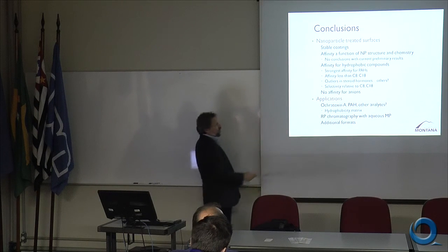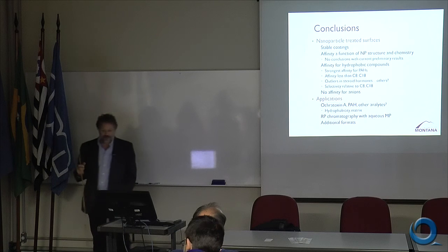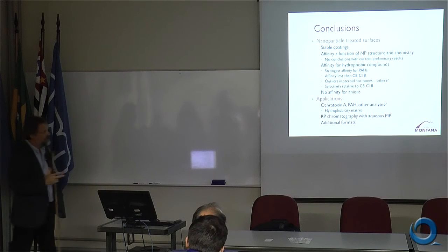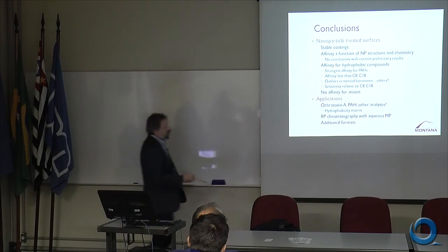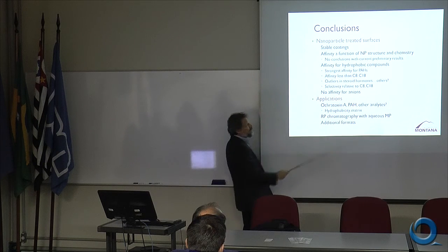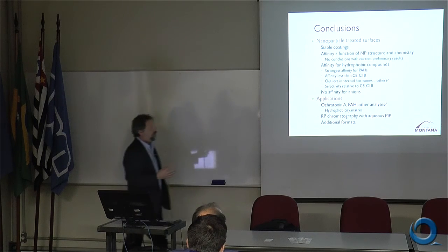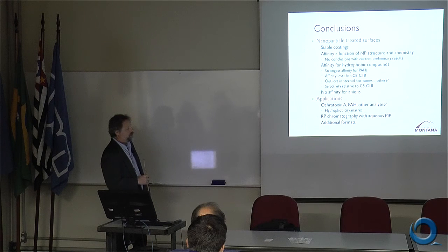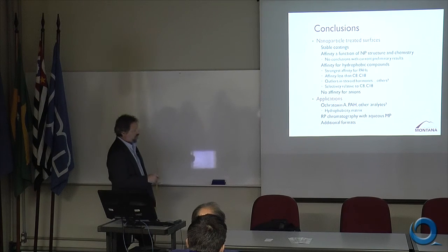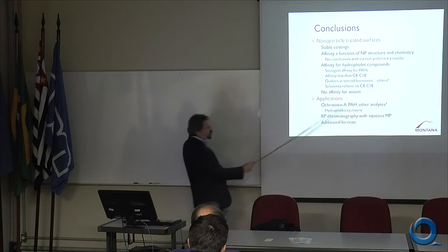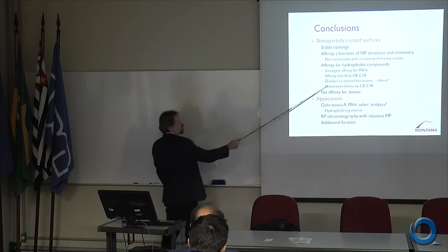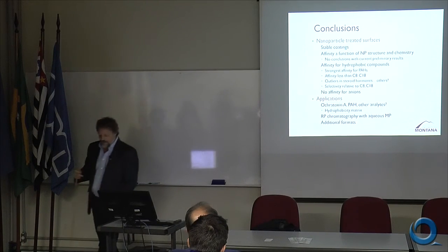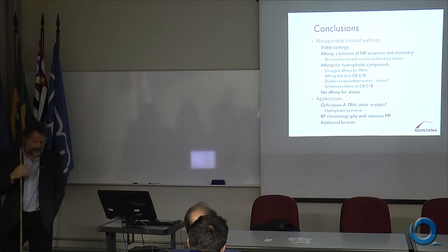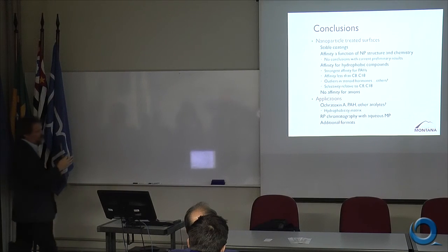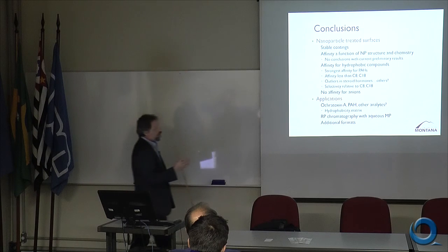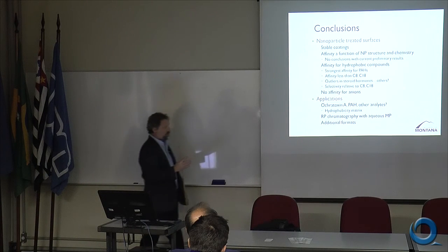The steroid hormones were clear outliers on this whole retention mechanism concept that we have, and there may be other compounds that would also give us very weak interactions, and this could be an avenue to look at in terms of the selectivity of these materials. Well, selectivity right there. There's no affinity apparently for the anions. As we go from a neutral compound to an anionic compound, we expected to see strong ionic interactions, and we just don't see it. It's just not there.